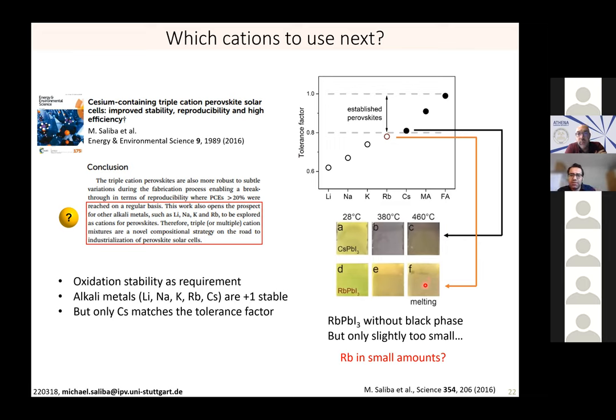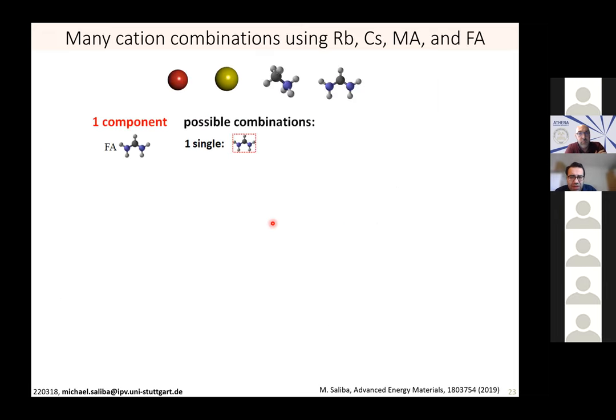But then the question is, maybe by adding rubidium in small quantities, they can become useful in the crystallization and formation of the perovskites. And so we started looking at it. And this put us in front of an interesting problem. In all of these compositions, we fixed formamidinium because it's thermally stable and it has a beneficially redshifted bandgap. And then we started adding systematically the other possible cations. We understood very well what happens when cesium is added, so we have a triple cation. But then when we add rubidium, what is the correct approach?